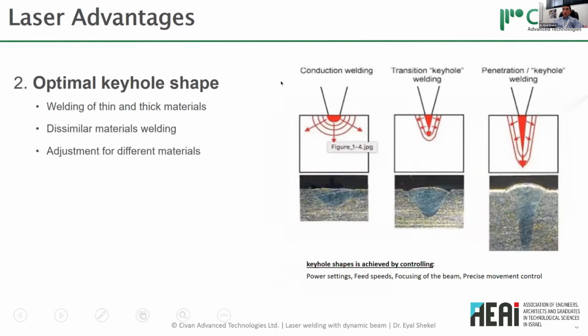You can also control the keyhole shape. You can control the keyhole shape by basically controlling the power, the feed speed, the focus of the beam, and so on. And you can have different shapes of the keyhole. This way, you can optimize the keyhole for the different welds that you want to do of different materials. If you want to weld dissimilar materials, you can adjust every parameter for the material that you want to weld.